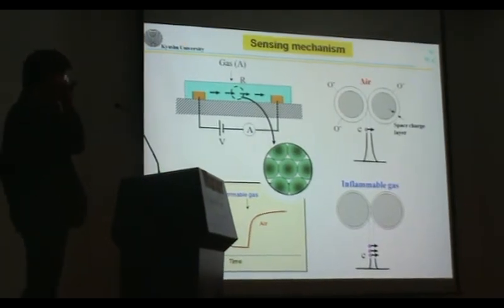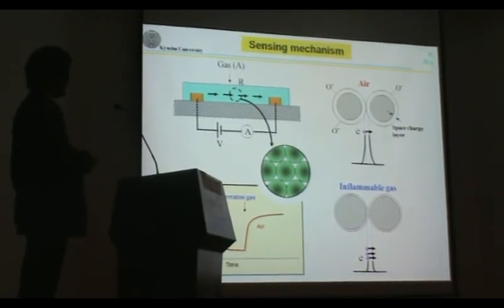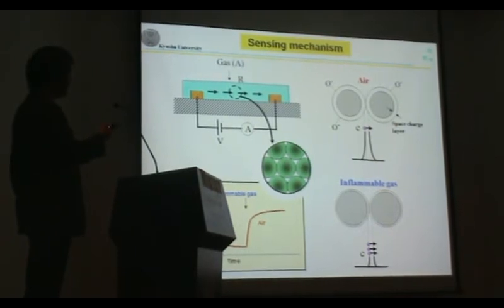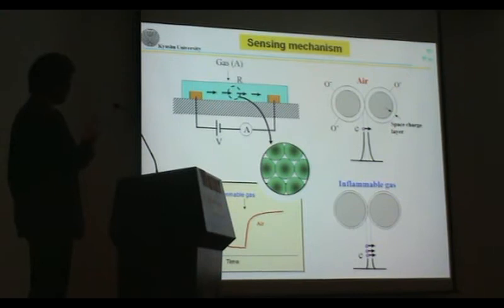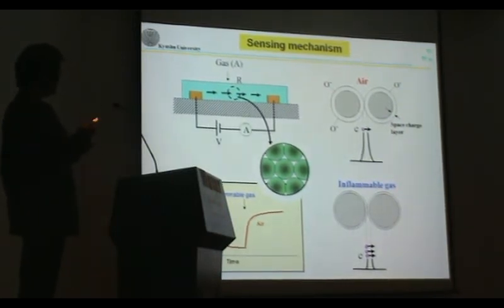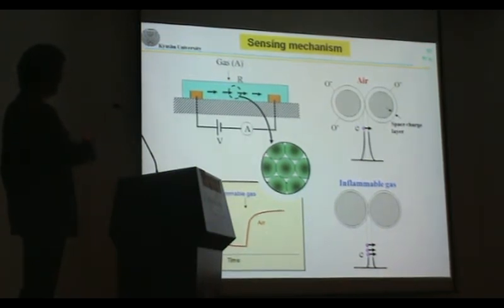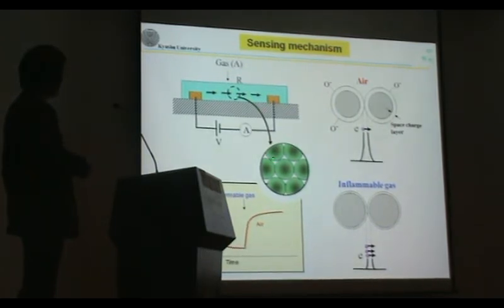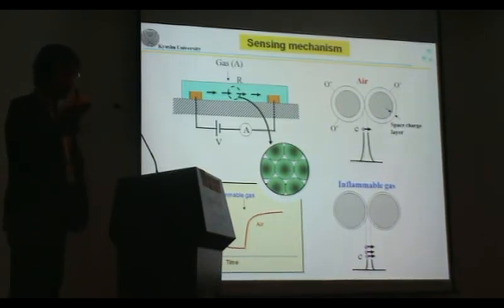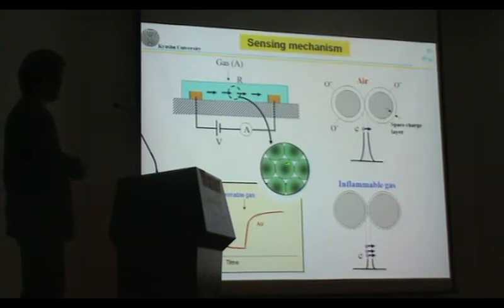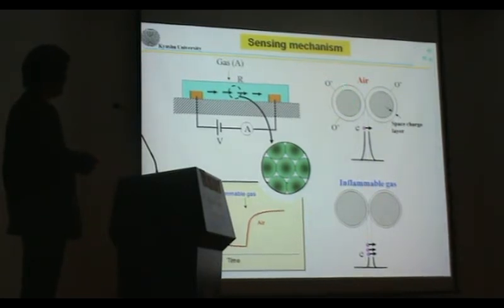I'm going to show the gas sensor's principle and mechanism. The semiconductor gas sensor consists of metal oxide powder. We deposit that powder on an alumina substrate with a gold electrode here. This film consists of these ceramic particles. The oxygen molecule in air is adsorbed on this particle. The metal oxide is a semiconductor material operated at high temperature. The oxygen molecule is adsorbed on the surface as O minus, so electrons move to the oxygen.